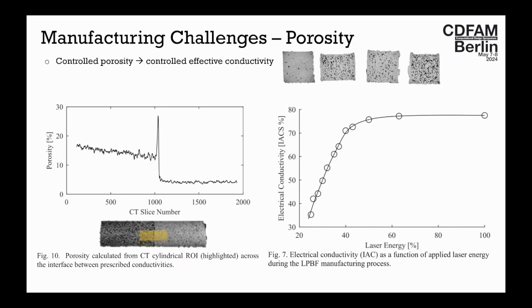I mentioned earlier that we've started to use porosity to our advantage. So one reason why porosity is important is because we can change the macro scale electrical conductivity of a material. So we can make a piece of copper electrically look like a piece of aluminium. The reason that's important is because the skin depth, which dictates where current flows during alternating current operation, effectively dictates how the losses are manifested within the device. And so if we can control the conductivity, we can control that behavior. So we've shown that we are able to do this repeatably and reliably.